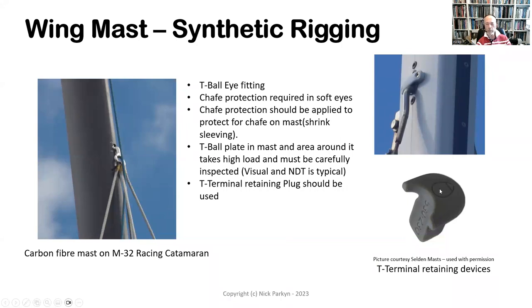We can see two different methods here. One is this kind of rubber plug that should be inserted. If you look at the picture on the left, one is not present, but typically one would like to see that. And then we can see in the picture at the top right that there's a more permanent type of locking bar applied to that T-ball fitting. Now, also the T-ball plates where they go into the mast are a high load area, especially when you apply them to carbon fiber masts, and really visual as well as non-destructive testing is typical, especially on carbon fiber masts. On aluminium masts, you will be able to see if that area has been overloaded.